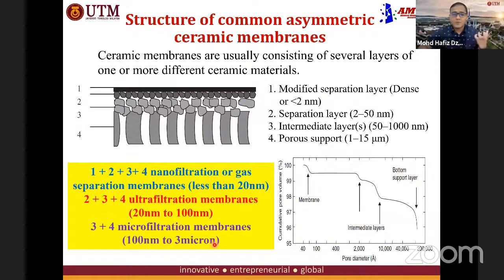For example, if you would like to produce a microfiltration membrane, which normally has quite a big pore size, probably 2 layers, the support layer and the intermediate layer, are enough to make the pore size within the range of microfiltration. But in order to further reduce the pore size of the membrane, for example for ultrafiltration, you probably have to add 1 more layer. For nanofiltration, you have to add another layer. So the layers become more and more if you would like to reduce the pore size of the ceramic membrane.